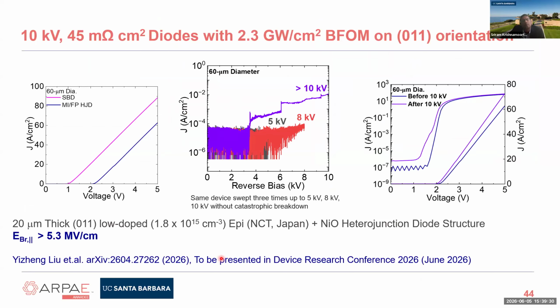And more recently in my group, we've been able to push these heterojunction diodes to about 10 kilovolt with reasonable on resistance, translating to a figure of merit that's very close to the silicon carbide theoretical line. And this is a diode that survived 3 sweeps and even more, like 10 kilovolts. And this is basically the characteristics before and after the sweep. And this is 20 micron thick epi, and if you translate this to an electric field at the junction, it works out to be something around 5.3 megavolt per centimeter.